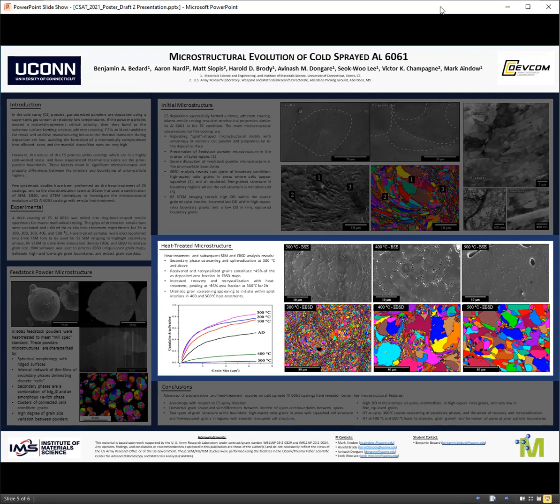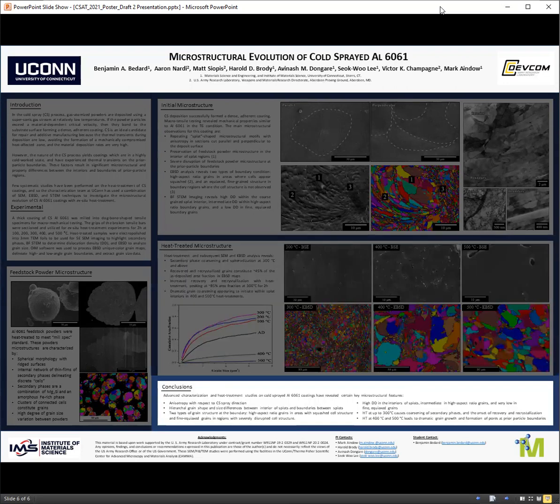And finally, at 500 degrees Celsius, there appears to be outgassing and pore formation in the prior particle boundaries. In conclusion, this poster is a summary of a systematic post-deposition heat treatment experiment on thick, cold spray coatings of aluminum 6061. Three distinct microstructural regimes are defined within the gas-atomized microstructure: coarse-grained interiors, squashed cell boundaries, and recrystallized boundaries. And three behaviors are tracked with respect to heat treatment: secondary phase coarsening, grain refinement, and pore formation.